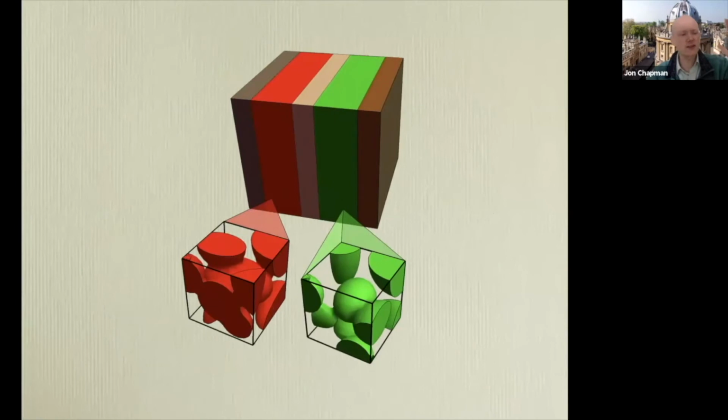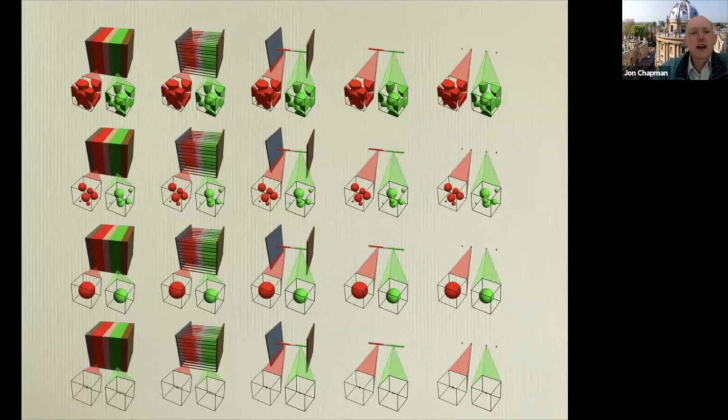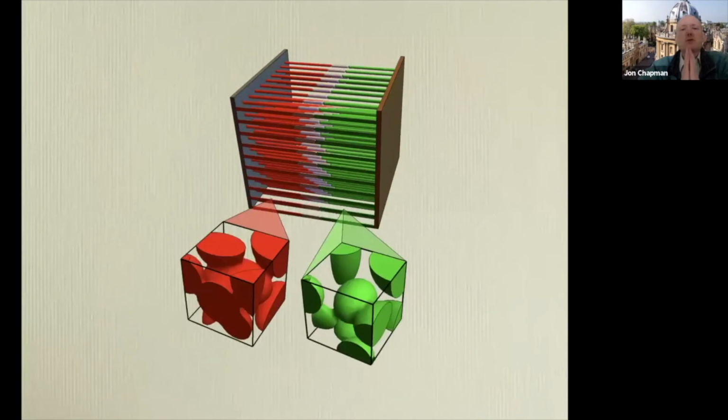So this is the 3 plus 3 that I'm starting off with. If I go to the next one on the left, this corresponds to taking the limit in which the aspect ratio of the cell is large. Typically the distance between the current collectors is much smaller than the lateral dimensions of the current collector, but the conductivity of the current collector is much higher than the cell.